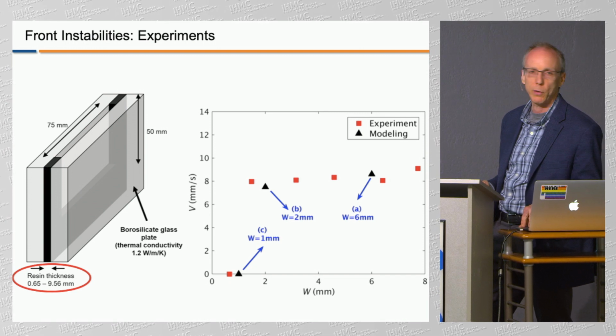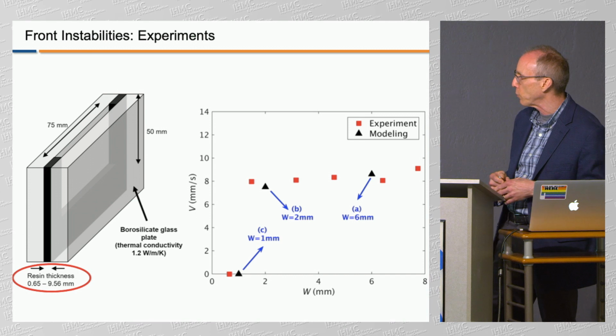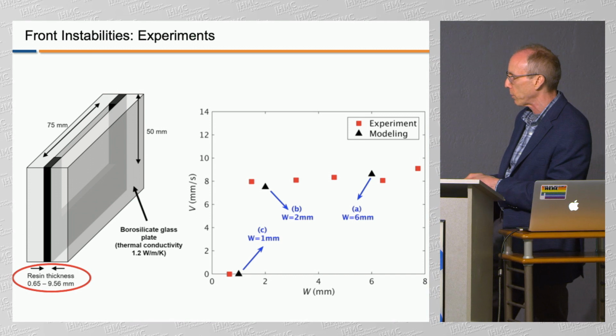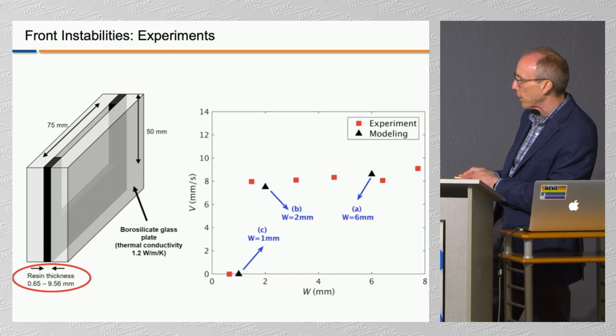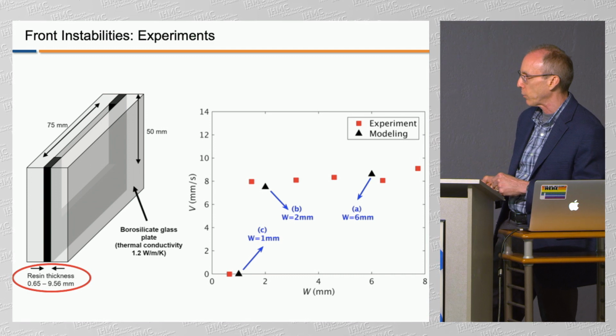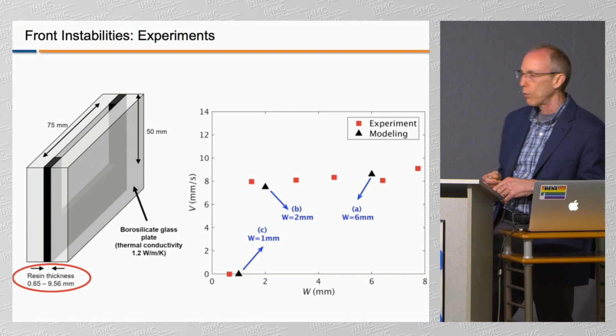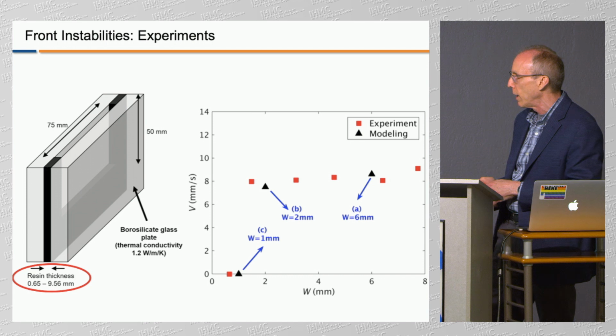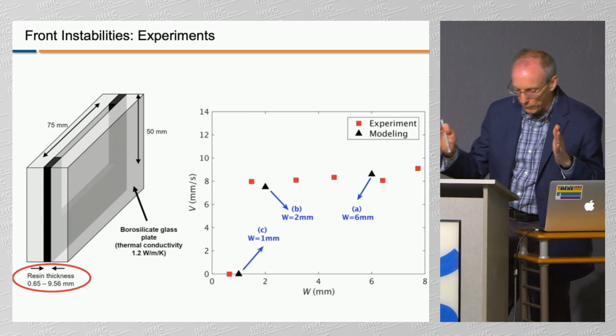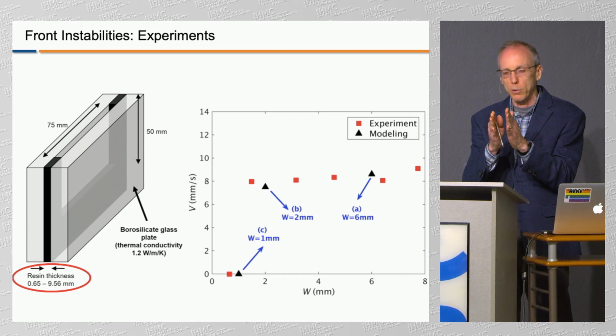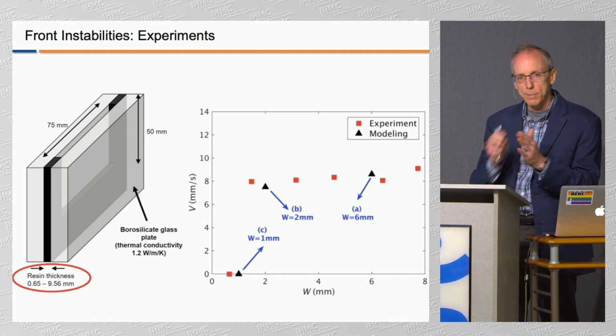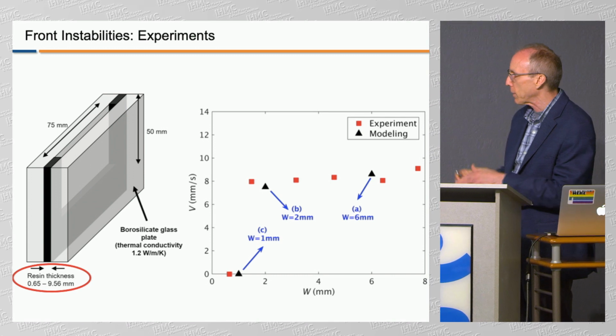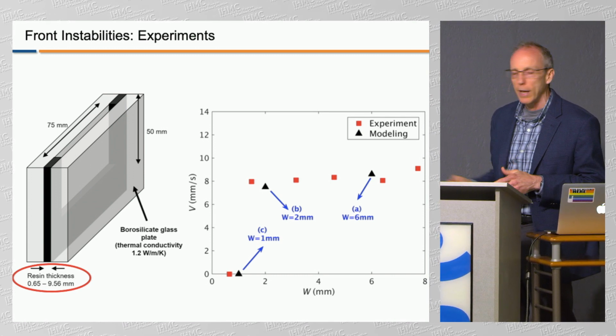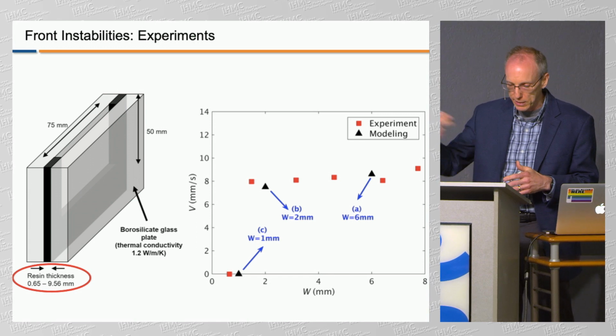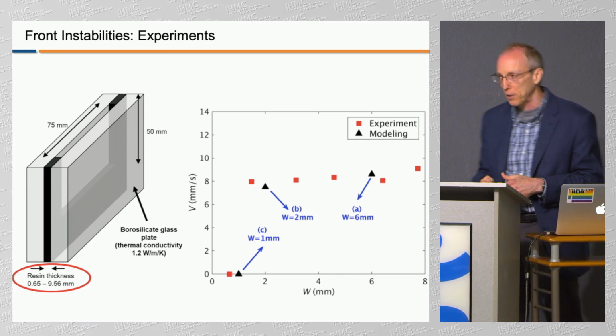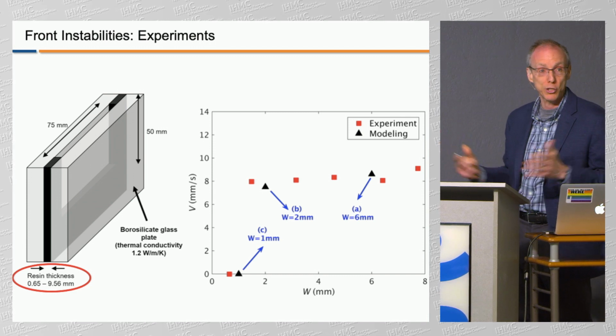But here was an experiment that we were trying to model in the lab. Philippe Gabel, who I showed on the first slide, is our computational person. And all we were doing is, this is a glass on the left and on the right, and it's a sandwich, and in the middle is the liquid monomer that's going to undergo frontal ring opening metathesis polymerization. And what happens is, if you reduce that gap smaller and smaller and smaller, eventually all the heat that's being generated from that reaction is transferred into the glass. And so then the front doesn't propagate anymore because it doesn't carry on to that next cell, like I showed you in that stretch slide.